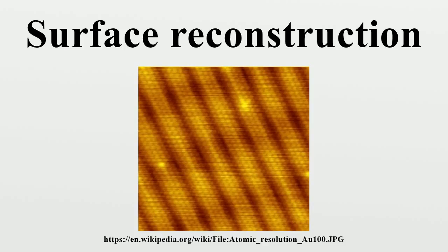However, this rotation disappears in a phase transition at approximately T equals 970 K, above which an unrotated hexagonal structure is observed. A second phase transition is observed at T equals 1170 K, in which an order-disorder transition occurs as entropic effects dominate at high temperature. The high-temperature disordered phase is explained as a quasi-melted phase in which only the surface becomes disordered between 1170 K and the bulk melting temperature of 1337 K.